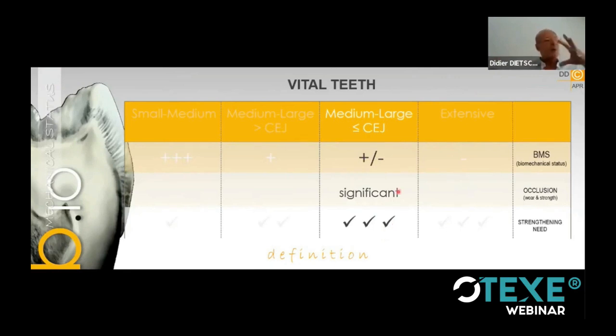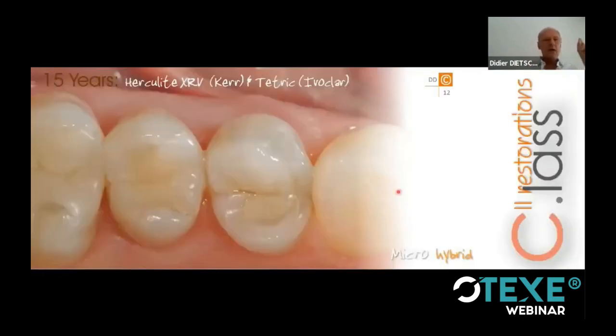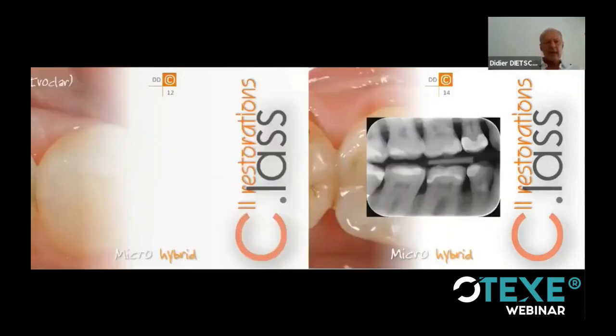We have also a significant part of the occlusion on the restoration. So we understand that, again, the biomechanics here might play a significant role. I'll show you only a few images here: 15 years follow-up of microhybrid restorations with cavities below the CEJ. You see more visible and severe degradation of the margins. Maybe also some functional risk factor, because you see a large wear facet here. It's nothing dramatic, but it doesn't look as good as the previous case.